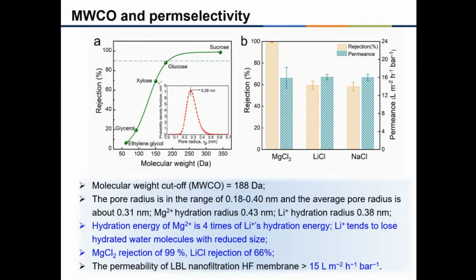The hydrated radius of lithium is 0.38 nanometer, smaller than that of magnesium, 0.43 nanometers, and the hydration energy of magnesium is 4 times the lithium hydration energy. Lithium tends to lose hydrate water molecules with reduced size, so the rejection of magnesium was the highest, 99%. Lithium rejection was 66%. Interestingly, the permeability of the LBL nanofiltration hollow fiber membrane is higher than 15 LMH per bar.